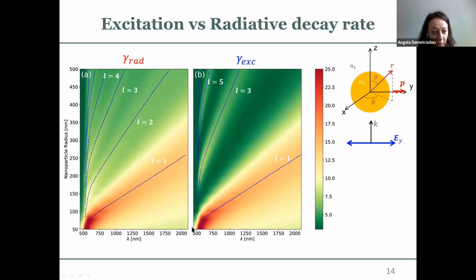non-quasi-static elements. And here what I'm plotting, in the x-axis is the wavelength, and in the y-axis is the nanoparticle radius. So down here, I'm just at the limit of the quasi-static limit. And you see there is some resemblance between the radiative decay rate on the left and the excitation rate on the right. As I make my nanoparticle larger and larger, you see that for the radiative decay rate, I have the first order mode, the second order mode, the third order mode, fourth, and so on. However, for the excitation rate, I'm missing all the even modes. So this is something universal that you see for all non-quasi-static metallic structures.